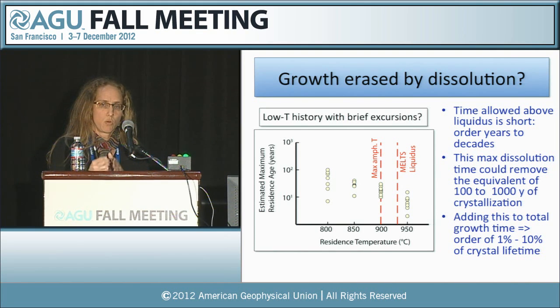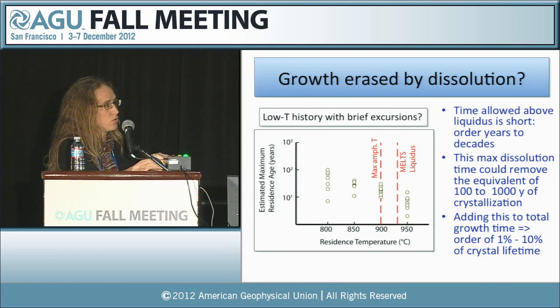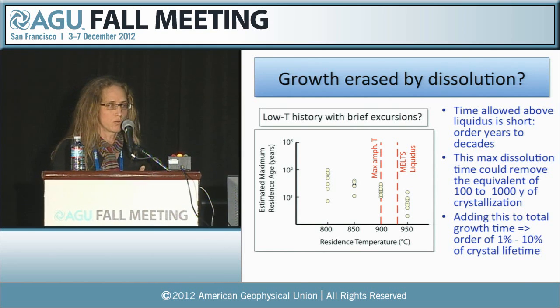So the equivalent amount of growth that would have been removed by years to decades of dissolution would have been 100 times more, so on the order of 100 to 1,000 years of crystallization could have been removed. If you add that to the total growth time, you're still talking about the order of 1% to 10% of the total crystal growth time or lifetime that the crystals spent growing.